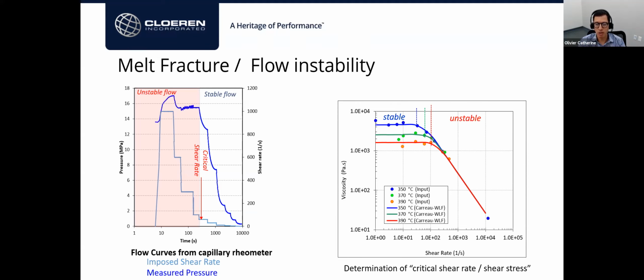The second phenomenon is more micro melt fracture. So we have melt fracture coming from the skin layers, and little by little, a little bit of material detaches from the film and starts to accumulate on the nose of the die. Okay. So depending on which one of those two it is, there are different ways to deal with that in your formulation strategy. If you think you have a little bit of melt fracture, then definitely a PPA, a polymer processing aid, like a fluoropolymer type, could be used to reduce the melt fracture and therefore reduce the buildup on the die.